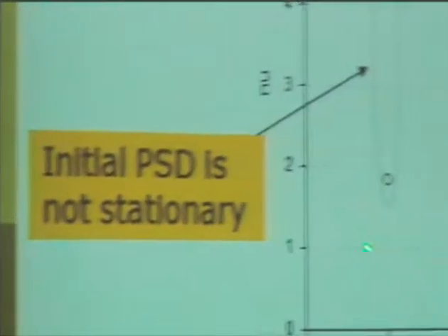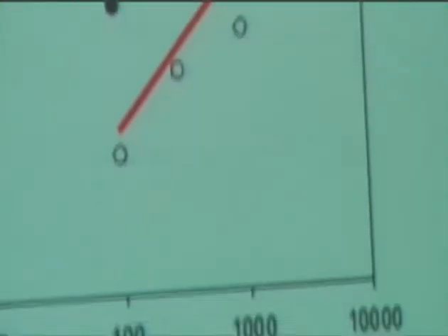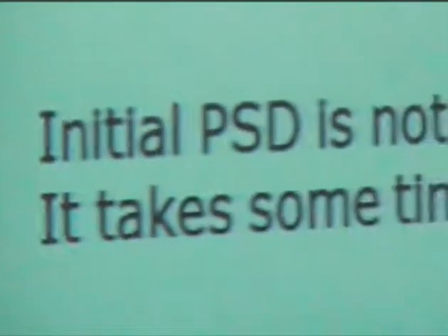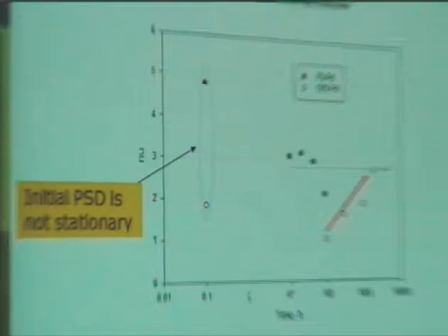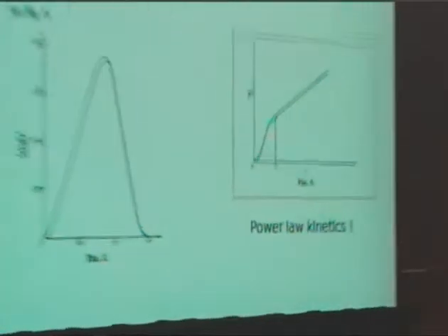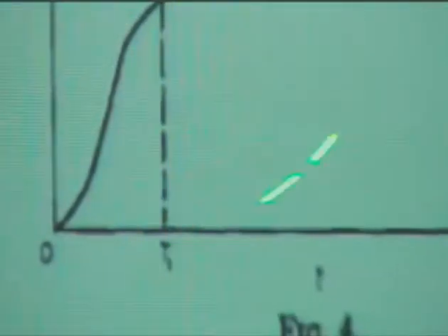Something that I may mention: the initial particle size distribution normally has parameter values that are different from the ones that you reach after a number of hours. I didn't mention that the solution that we're getting numerically is a stationary solution, so you need time for that stationary solution to develop. And actually, this is from the article by Lifshitz and Slyozov, and they correctly said that their prediction is valid just after an initial period of time when the distribution is developing.